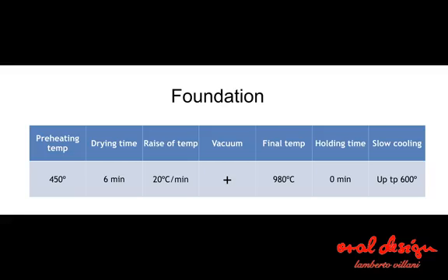For the foundation, I will go to the final temperature 980. It could be enough 950, but I want to be sure. I have 980, 0 minutes hold, but I have to cool down very slowly until 500 or 600 degrees. In this way, I have the first real bonding of my ceramic with the zirconia framework.